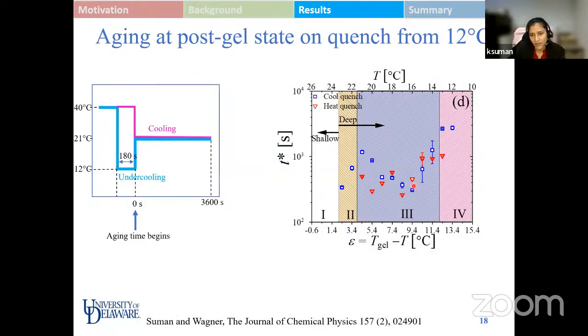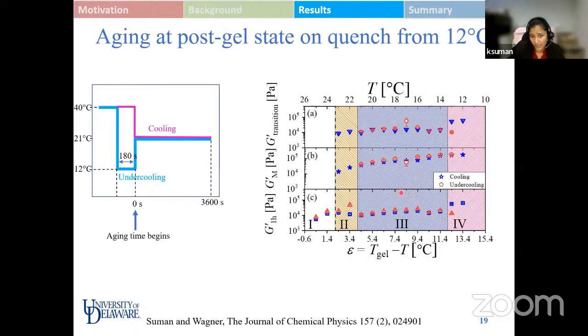And this says that the initial temperature does have a role in determining the final transition time of the system. We also characterize the different modulus values at the different stages of transition, which is at the end of aging behavior, the maximum achieved during the aging behavior, and at the point of transition during the cooling and the heating protocol. And it can be seen that the values are pretty much in close proximity, which suggests that although the transition time scales are slightly different, the value of modulus, which is the final value of the arrested state or the transition state, is equivalent in both the protocols.